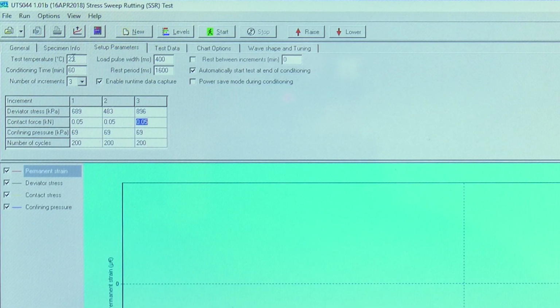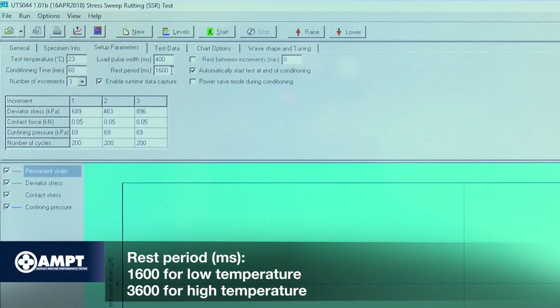Under Setup Parameters, enter the appropriate test temperatures for the testing location, conditioning time, 60 minutes, and number of increments, 3. The load pulse width should be 400 milliseconds. The rest period should be 1600 milliseconds for low temperature and 3600 milliseconds for high temperature. For the increment table, which covers deviator stress, contact force, confining pressure, and number of cycles, refer to the recommended values in the AASHTO TP134 standard.